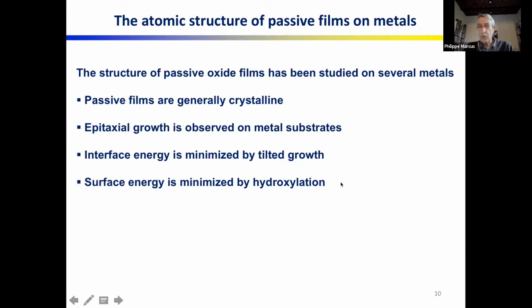The work I've shown was done on single crystals to get rid of grain boundaries, but obviously these conclusions can be extended for each grain at the surface. So these conclusions here are not, of course, restricted to single crystals. They would apply on individual grains of a polycrystalline materials. As for grain boundaries, there are studies in parallel because the reactivity of grain boundaries is different from the reactivity of grains. Of course, we need to know about alloys and not only pure metals.